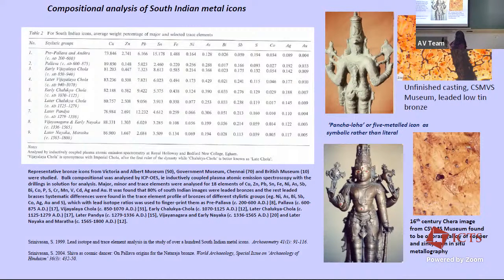And this is just to show you an unfinished bronze. This is what happens when you have all these runners and so on intact. And you see here the sprue at the back. So in the earlier times, they were actually pouring from the back of the image and so on. So different methods of casting, which would have, in this case, it was totally damaged and has been kind of set aside. And of course, each of the castings is quite unique.